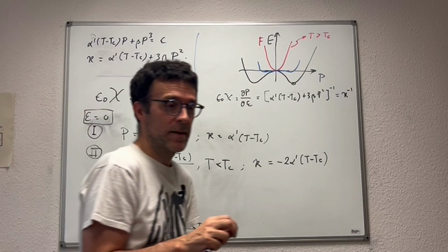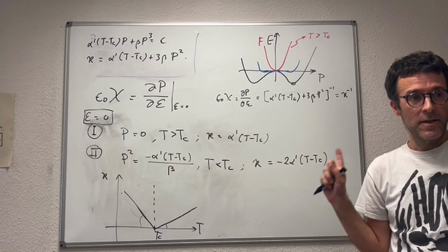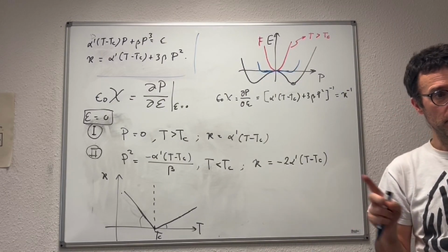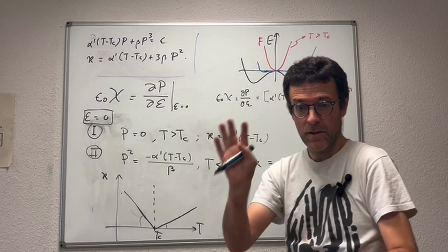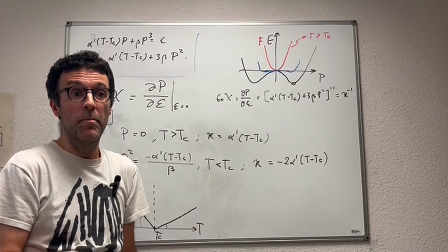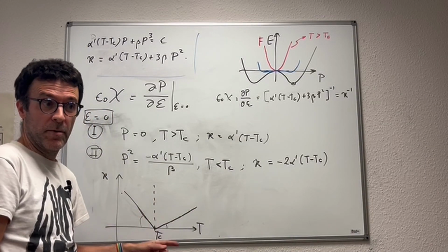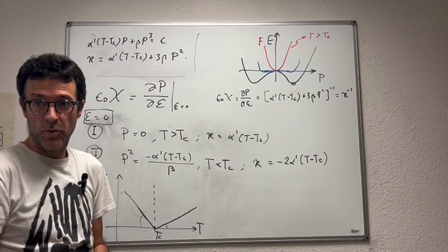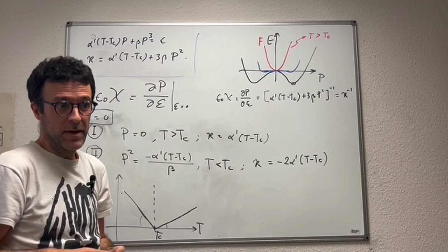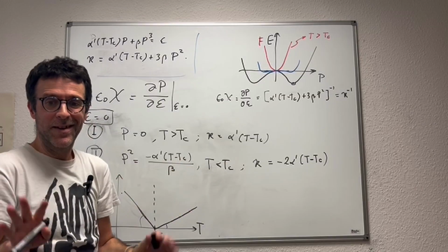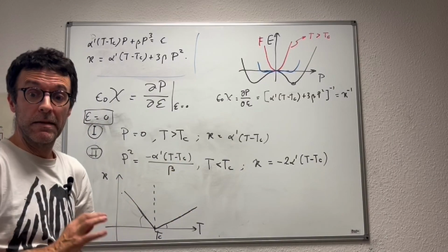Now, what is amazing is that for many ferroelectrics, this can be straightforwardly measured. You measure susceptibility as a function of temperature in a ferroelectric with a continuous or approximately continuous phase transition. You can plot the inverse of the susceptibility, and you will see approximately linear behavior with a relationship of slopes of approximately a factor of 2. This happens in many, many materials. In some of them, it's incredibly accurate. In others, it's an approximation, but this is still generally true.